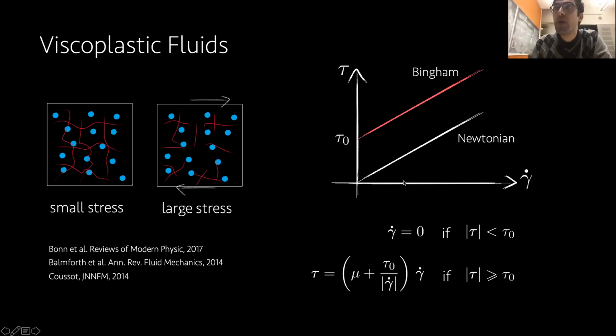The x-axis is my shear rate, the y-axis is stress. If you have Newtonian fluids, it's a straight line passing through the origin. The slope of the line is your viscosity. But if you have a Bingham fluid or a viscoplastic fluid, you have this threshold stress, this offset, and that stress is the yield stress. If the plastic viscosity is constant, you have a Bingham fluid, right? In tensorial form, you can write it like this: below the yield stress, the deformation rate tensor is 0, above it, you get deformation.